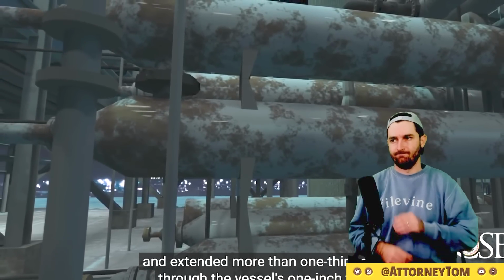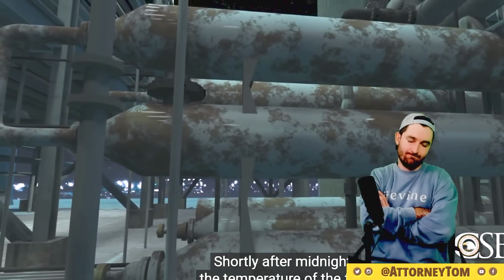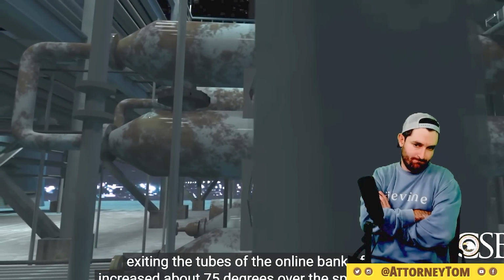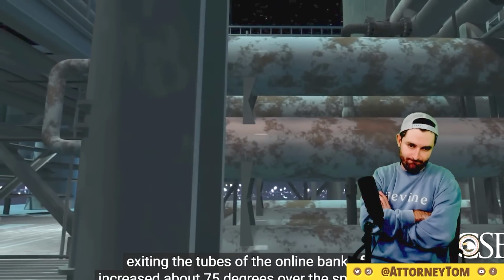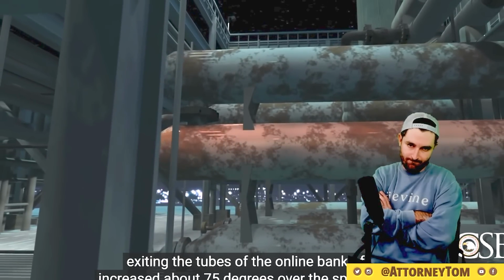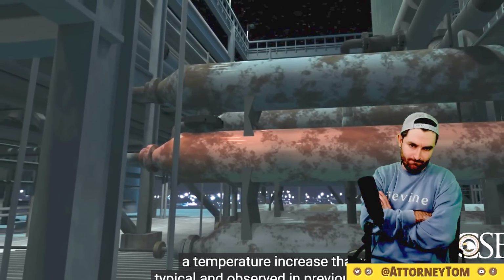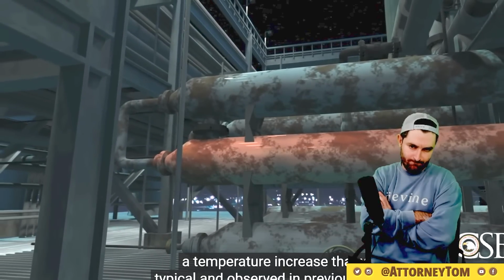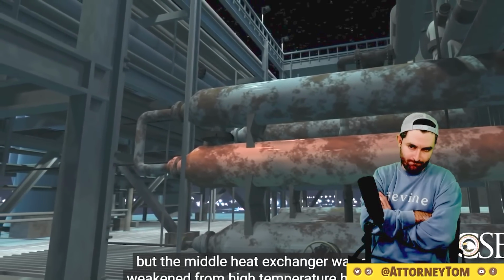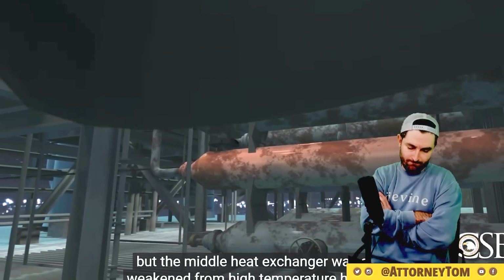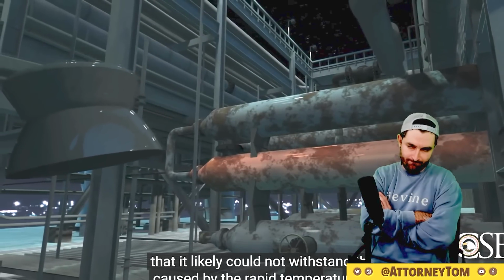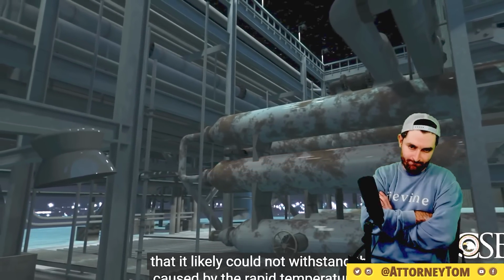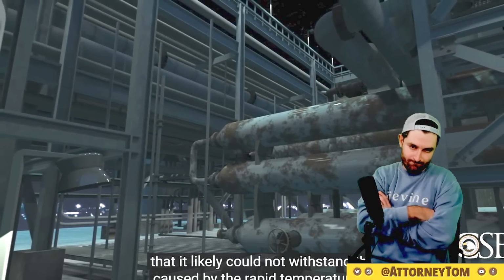Shortly after midnight, the temperature of the fluid exiting the tubes of the online bank of exchangers increased about 75 degrees over the span of 3 minutes, a temperature increase that was typical and observed in previous startups. But the middle heat exchanger was so severely weakened from high-temperature hydrogen attack that it likely could not withstand the stress caused by the rapid temperature increase.